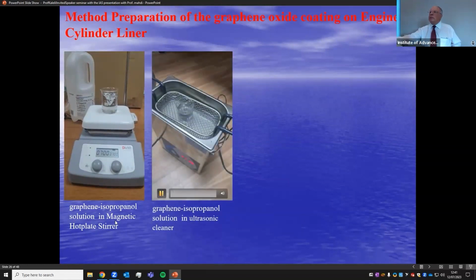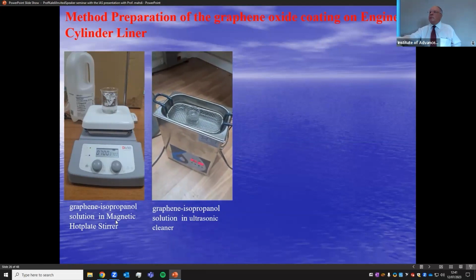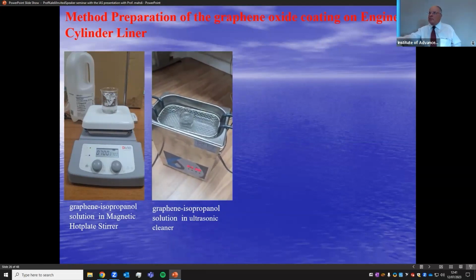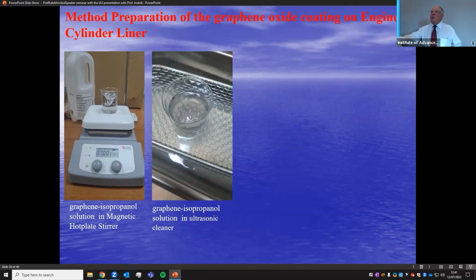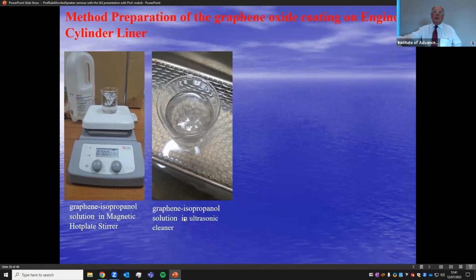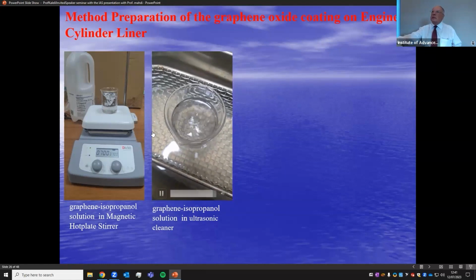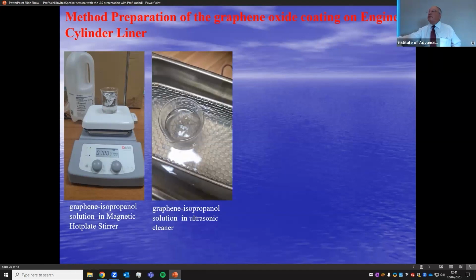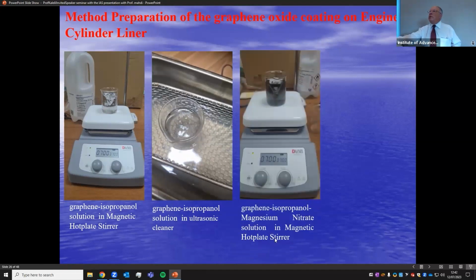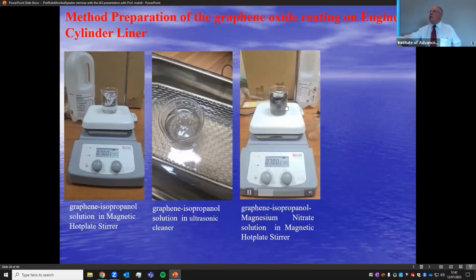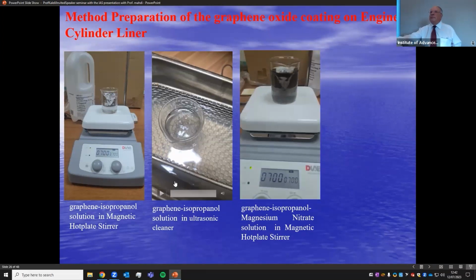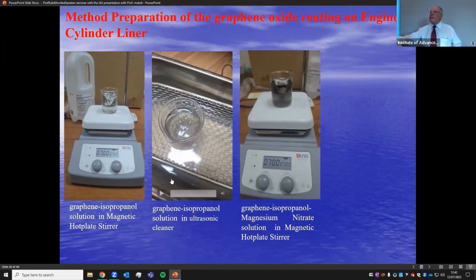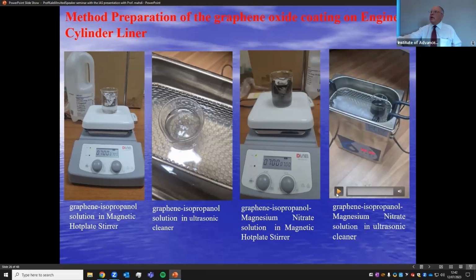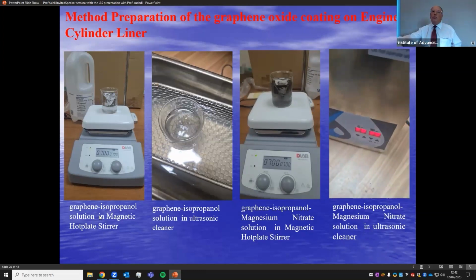Then ultrasonic cleaner. Magnetic stirrer and ultrasonic cleaner is very important. If you don't do it, you cannot succeed. It's very difficult. Then we added, according to the literature survey, magnesium nitrate, enough amount. You see the color starts to change. Then magnetic stirrer 30 minutes again. So this total is 1 hour, so 2 hours.